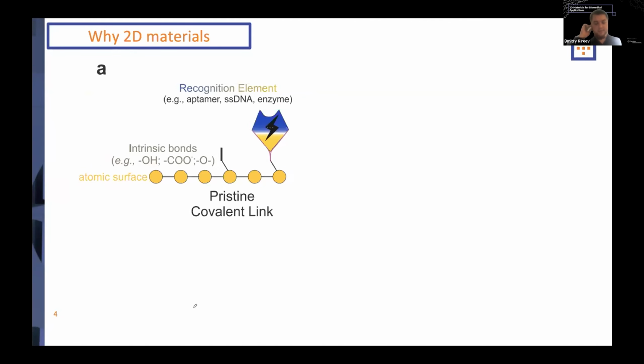And so let's say I would split the biorecognition elements, from the chemistry of the 2D materials to how you get the recognition element onto them, in 3 different ways. One, let's say you have a pristine covalent link. You have an atomic surface, which could be carbon, molybdenum, or silicon. In the case of silicon, it could be boron, whatever 2D material you're using. They would have their own specific intrinsic bonds. And in the ideal case, which is rather impossible, these intrinsic bonds would react to the recognition elements right away, and you have your biosensor in a single step.